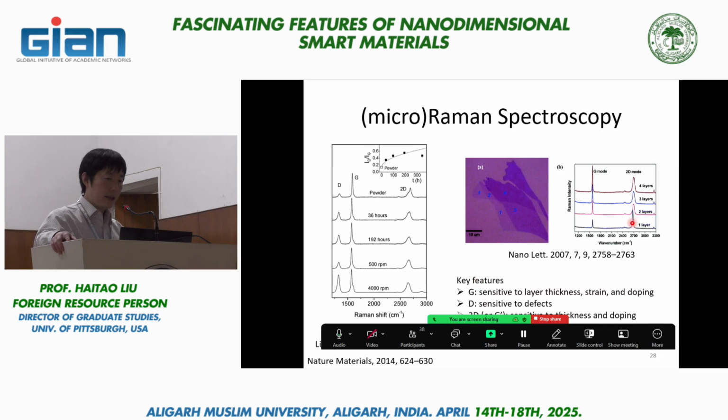You look at the spectra on the right-hand side, and these are 4 different spectra of graphene separated by the actual layer thickness. On the 1 layer graphene, you see 2 prominent peaks. There's one around 1580 wave numbers. That is the so-called G peak.